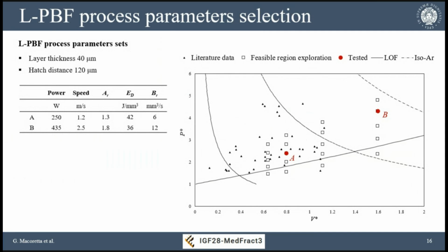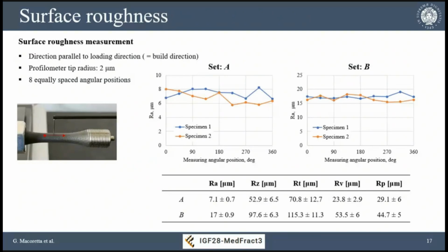But we also see a large increase in material defects. We measured surface roughness with a standard profilometer at different positions around the circumference of our fatigue testing samples. The surface roughness is almost constant as we rotate the sample—an advantage of using round samples, which with this powder show almost no effect from orientation relative to the recoater.